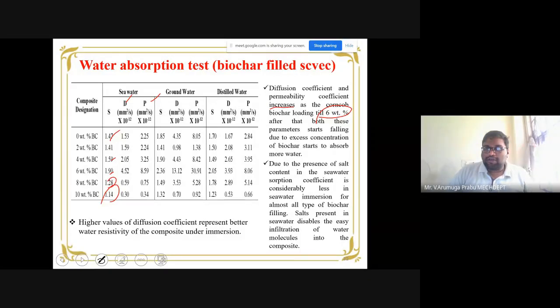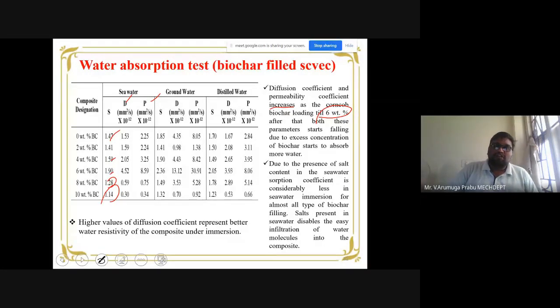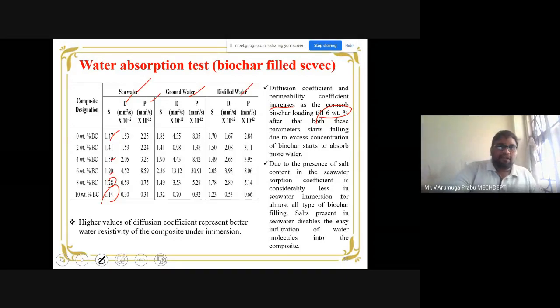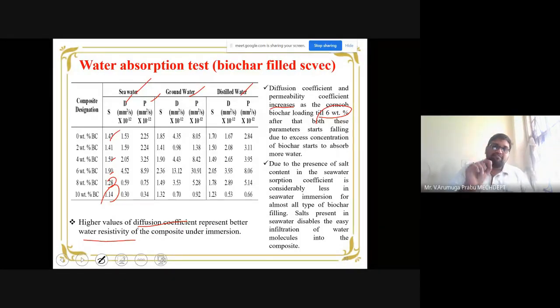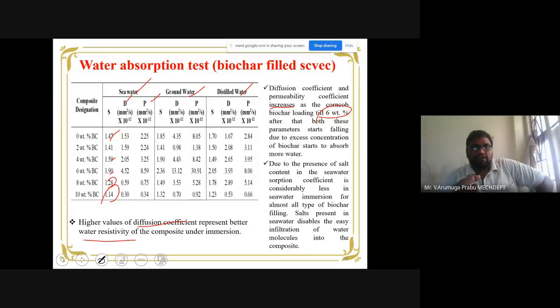Both these parameters start falling mainly due to the excess concentration of biochar, which starts absorbing more water. Okay, and another main reason they point out is the presence of salt content in the seawater, so the absorption coefficient is considerably less in the case of seawater. Also, the salt present in the seawater disables the easy infiltration of water molecules into the composite. So we consider three cases: seawater, groundwater, and distilled water. And a higher value of diffusion coefficient will always show better resistivity of the composites under immersion, which is the very highlighting point that all of us must be aware of while doing the water absorption test.